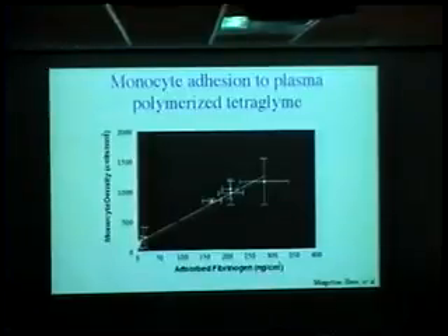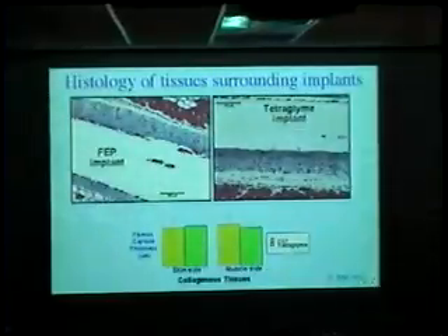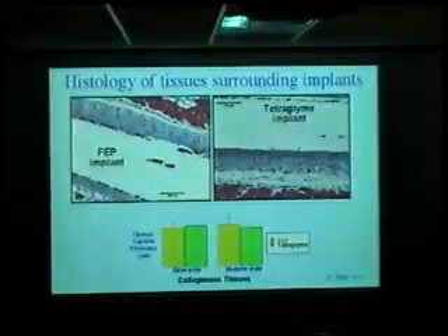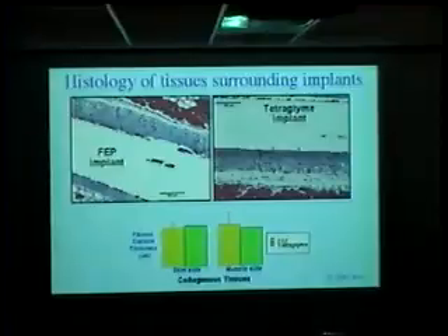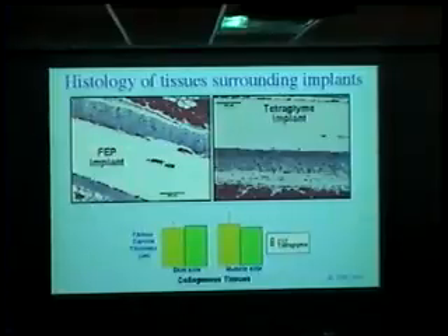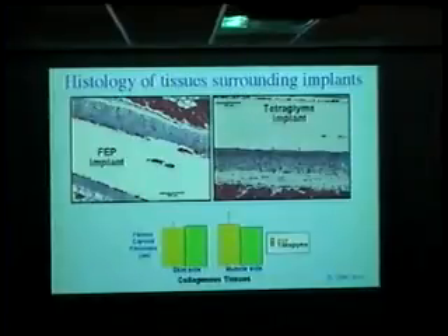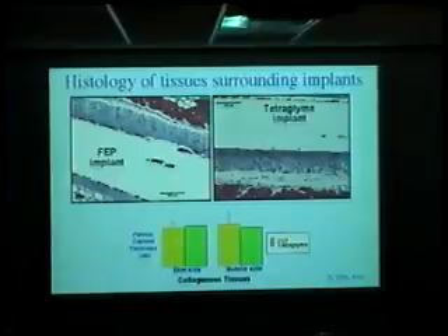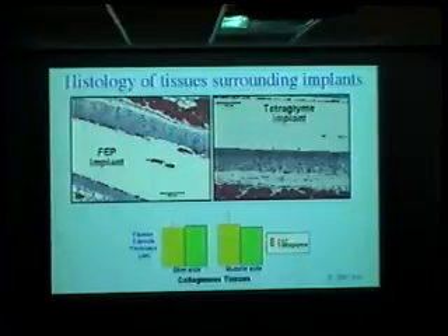So one of our Ph.D. students, Ming-Xiao Shen, implanted these. And we got actually quite a surprise, which is opening up some new horizons for us. This is an FEP implant. FEP is fluorinated ethylene propylene, a Teflon implant, the control. And here's the tetraglyme implant. And this blue is the stained collagen. In fact, if we look at the thickness of the collagen capsule for the FEP Teflon and the tetraglyme, they're essentially identical.